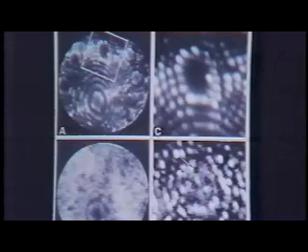Much more effective way. This is a hydrogen image of the surface. Doesn't look very good at all because hydrogen, curiously enough, at 20 degrees Kelvin doesn't stick, so shouldn't form an image at all, but it does. And the reason it does is because it not only sticks chemically to the surface, but it forms a field-induced dipole-dipole bond. The first known example of an effect called field adsorption. The higher the field is, the stronger the stuff sticks to the surface.